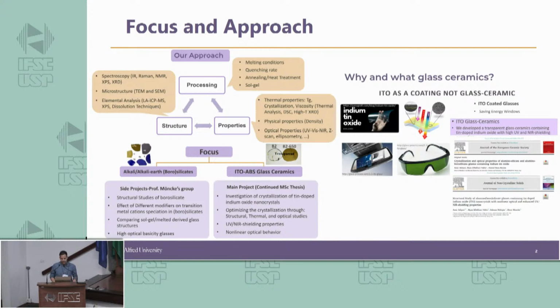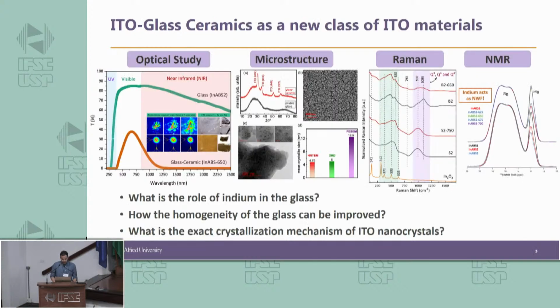spectroscopic techniques. And then mostly I'm focused on borosilicates and aluminoborosilicates, specifically aluminoborosilicate glass ceramics containing indium tin oxide nanocrystals to develop materials that are transparent in the visible region, but with highly UV and near-infrared shielding properties. Nowadays, I'm mostly focused on linear and also nonlinear optical properties of these glass ceramics, and also I'm trying to understand as much as I can the structure and crystallization mechanism in these glasses through Raman and NMR techniques.